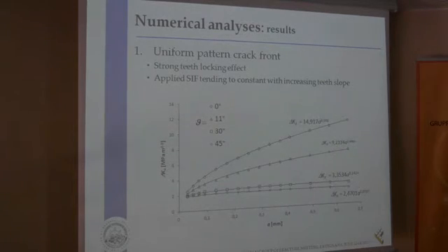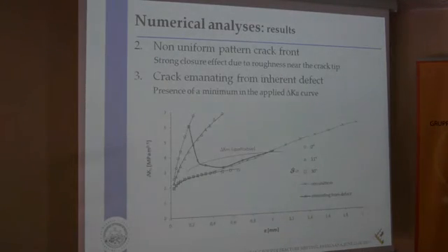In this picture are reported the results in terms of applied stress intensity factor, mode 2, for the constant slope models, which show a very significant effect of this parameter on the stress intensity factor, which means a very important locking effect. In this picture is reported the non-uniform model crack curve, together with some curves referring to different tip slopes, and the curve referring to the inherent defect.